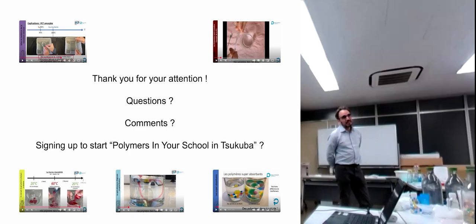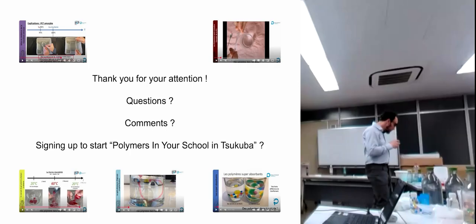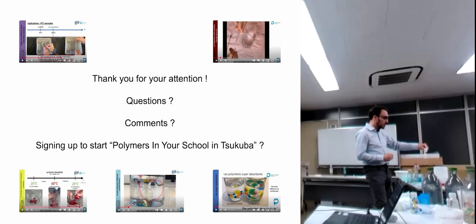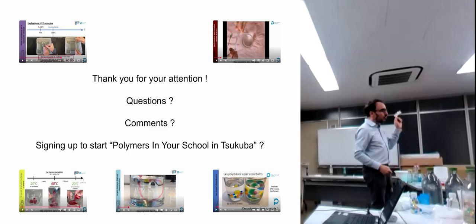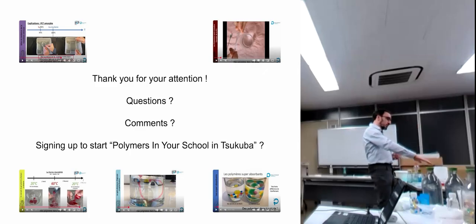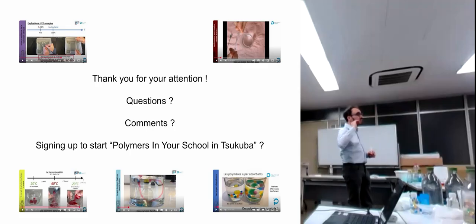At Polytech Grenoble, during some of my lectures, I show that we can control the whiteness of the PCL by controlling the shape of the crystals. So I could, for example, melt half of this in hot water. This is also a good way to show that the heat conductivity is very bad, because you pour this in hot water and just like this it melts and this stays crystalline. And if you put it back in liquid nitrogen, for example, you have a much lower crystallization temperature. You cannot keep it amorphous, it's impossible because it crystallizes very fast, but you will have a lower crystallization temperature and you will have much more nucleation.